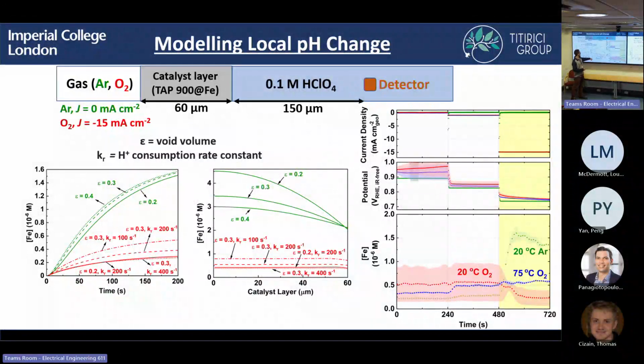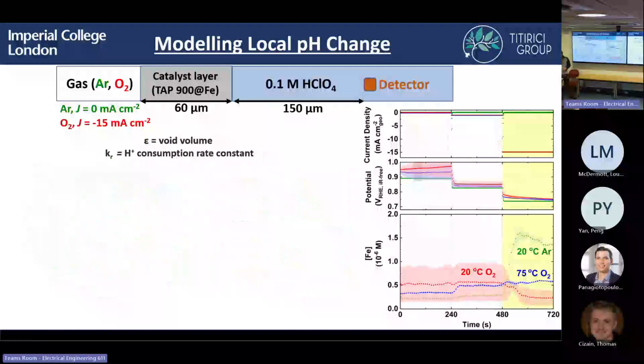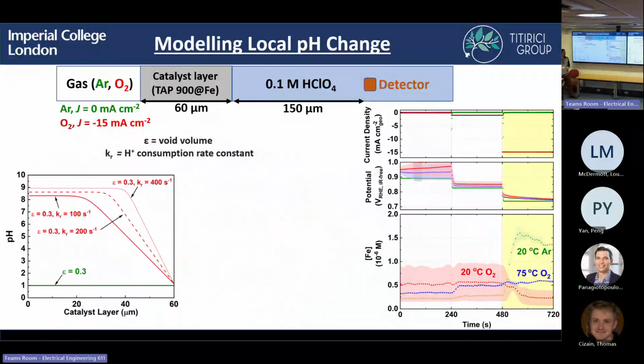And we see that when we look at the catalyst layer, so going from this side is 0, this side is 60 microns, we see that in argon there seems to be a bit of a distribution in the ion concentration, whereas in oxygen it's fairly constant. And the really interesting thing is, if you then consider the concentration of protons or the pH, in argon, obviously, as you expect, there's no consumption of protons because there's no reaction happening. So we just have a pH of 1 because that's the pH of the electrolyte.